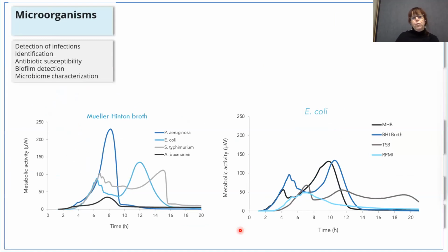We can look at, for the microorganism, how you can identify your microorganism. So here are different bacteria. They are grown in the same broth or the same media, and you can see that the different bacteria will have completely different profiles. So this is a way to identify the bacteria, what type of species are there. We can also see that depending on the media composition, the same bacteria, like here in this example, the E. coli, will grow with a completely different profile in different types of media. So this can also be used for identification. If you have some bacteria that grow better in other media, you can use specific media to look at how they grow in that media.